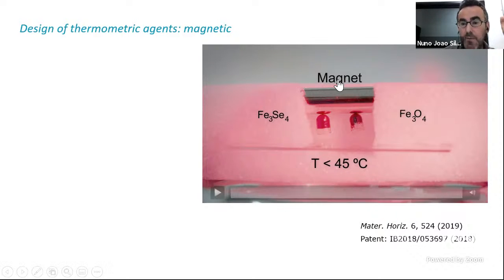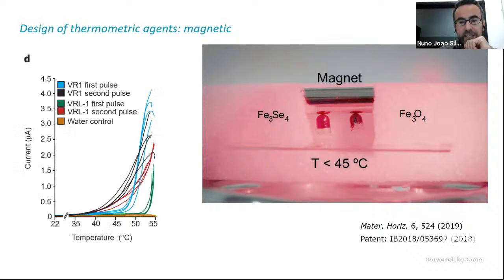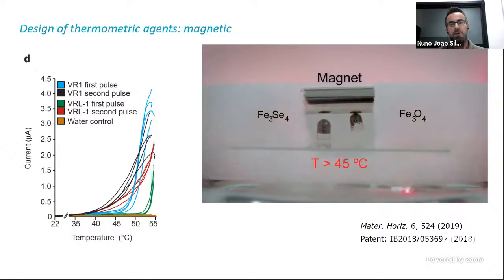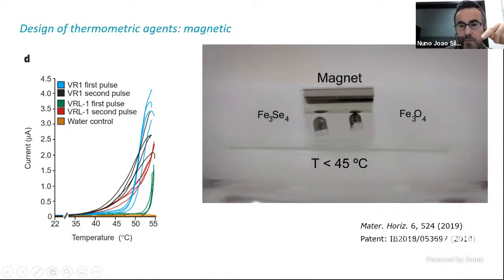And so normally magnets are magnetic at room temperature, but we came up with these magnetic nanoparticles that change their magnetic state when they cross 45 degrees centigrade. So basically they are magnetic below this temperature, and once you cross this temperature they become non-magnetic, and then if you come back again, they become magnetic again. So you see them, they just go back to the magnet, they become magnetized. And they do that at 45 degrees Celsius.